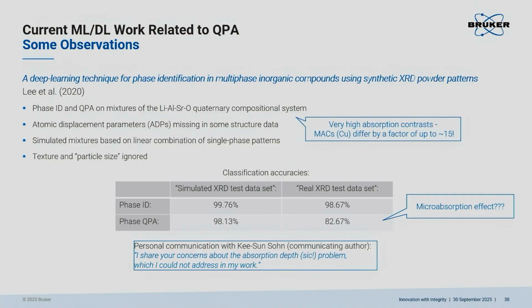So they say, deep learning technique for phase identification in multi-phase inorganic compounds using synthetic XRD powder patterns. From the terminology, often you can guess instantly that they are not powder diffractionists. We would never call that synthetic. Most importantly, what they do is they simulate mixtures by linear combination of single patterns. Sure, that is of course what you would do. What else could you do? Microabsorption, you cannot correct it, so you also cannot predict it.